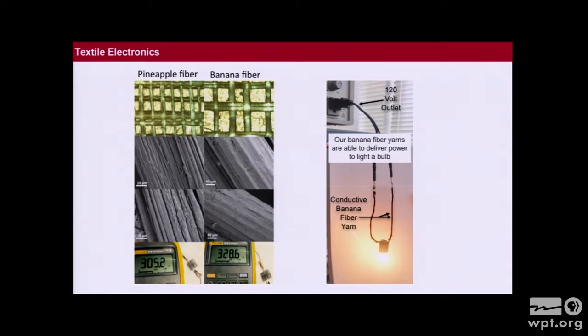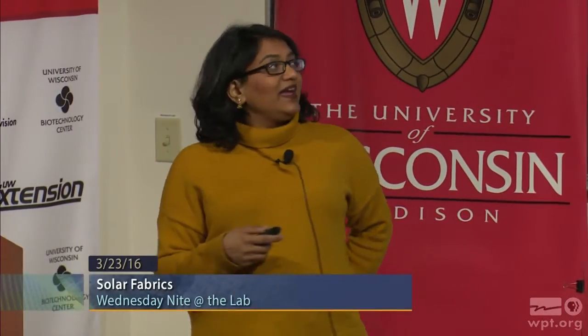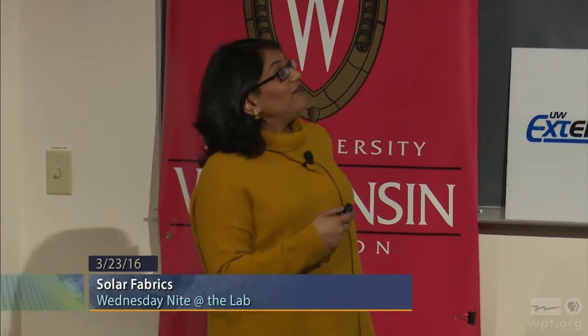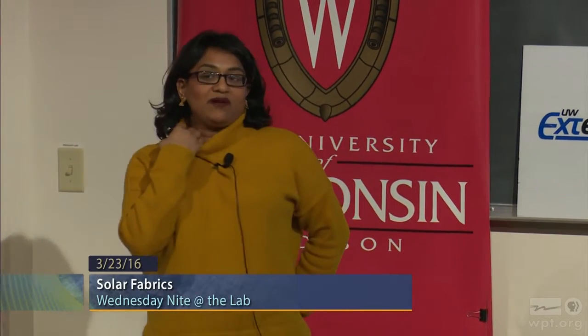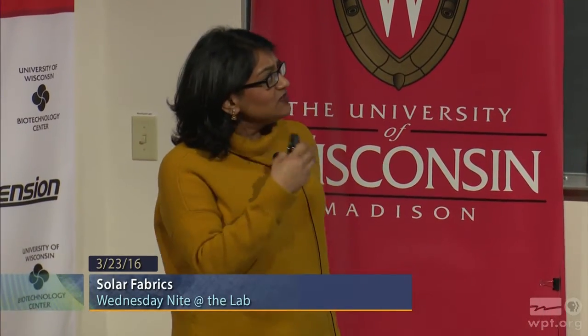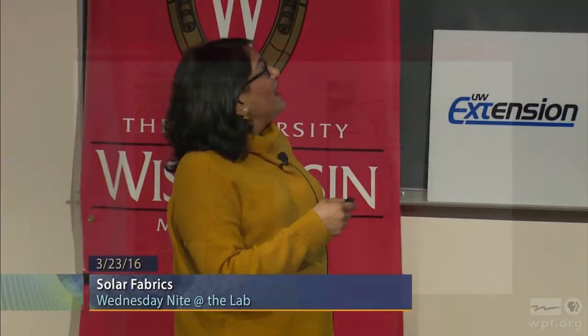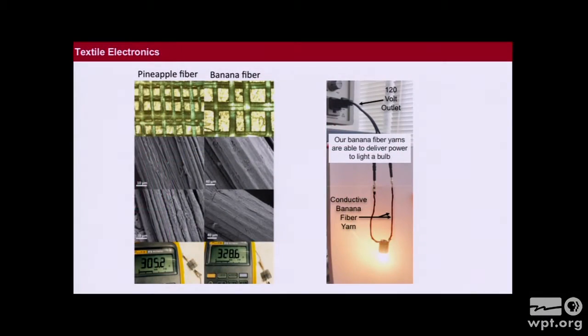Pineapple fabric is the material that forms the national uniform of the Philippines. And these are both what she tells me are bast fibers. So they come from the leaves of the pineapple and banana plants, respectively. And so you just dry the leaves and pull them apart, make a fiber, and then you could weave some very gauzy clothes out of them. And what you're seeing here are first optical microscope images, so you can see the blue color everywhere. You see the slightly blue-green pattern, because it looks slightly blue-green to the eye. And these are some SEMs. This is before deposition. This is after deposition, again, to show you the conformality of this process.